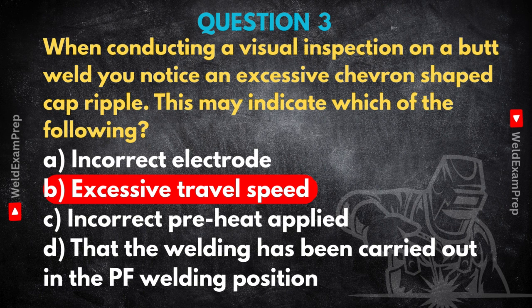Incorrect preheat. If your preheat is wrong, especially too low on certain steels, you're more likely looking for cracking, maybe porosity, or just a generally poor bead shape because the heat flows off, not usually this specific ripple. Right, different symptoms. And welding in the PF position, that's vertical up, that definitely affects how you weld. You need techniques to counteract gravity. You might get a slightly more convex bead, perhaps. But again, the excessive chevron ripple itself still points directly back to travel speed being too high for the conditions, whatever the position. It's amazing how much you can deduce just by looking closely. That ripple pattern is a direct fingerprint of the process speed, which really emphasizes the power of good visual inspection. It's your first line of defense, and often the most informative if you know what to look for.